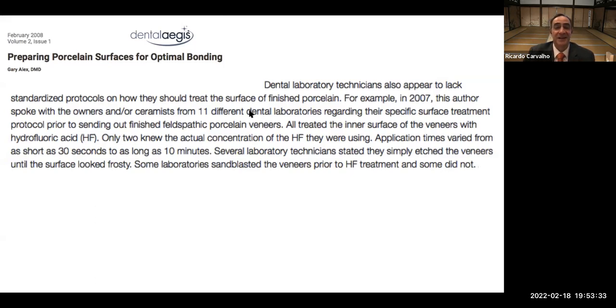And the result was amazing because, first of all, he didn't see any specific protocol in any laboratory. He learned that all laboratories always treat the intaglio surface of the veneers with hydrofluoric acid. Okay, that's fine. However, only 2 labs actually knew the concentration of the acid they were using. Among the different laboratories, the application times varied from as short as 30 seconds to as long as 10 minutes. So you can imagine how different the surface looks in these different scenarios. Probably a lot of residues, a lot of over etching in the cases of longer etching time. And several laboratory technicians stated that they simply etched the veneers until the surface looked frosty, right? Which is exactly what you don't want to do.